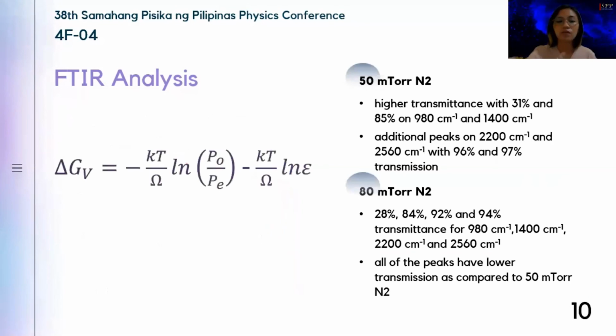Further increasing the pressure of the background gas increases the coefficient as seen in the equation. Increasing the pressure will lead to an increase in the epsilon, and this decreases the delta G sub V, which promotes coalescence, which can be seen as the lower transmittance of the film.